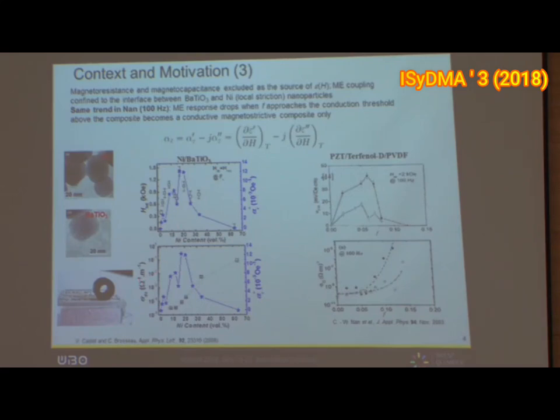When you compact both powders, you put some pressure, like a protocol, you can raise this compact like this, and you can cut the compact and make the characterization you want. Basically what we do is measure the variation of the permittivity, either the real part or the imaginary part, epsilon prime or epsilon double prime, versus the magnetic excitation.